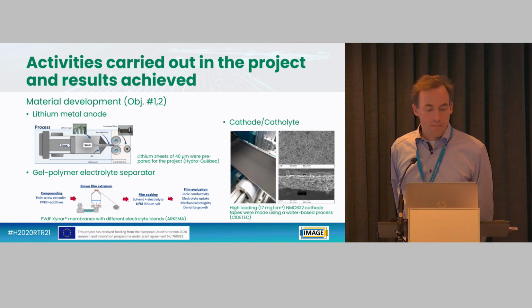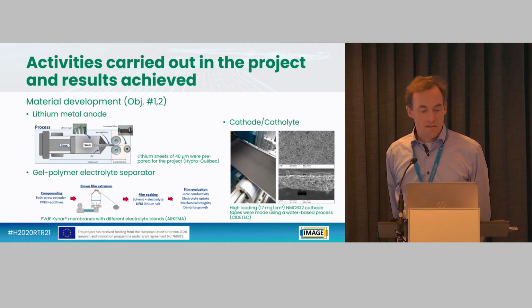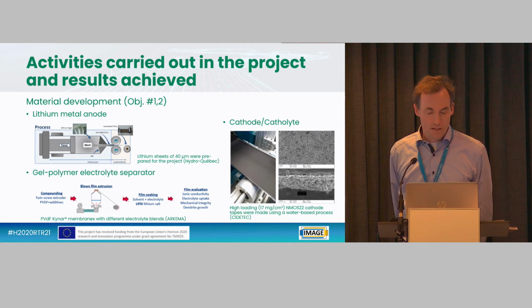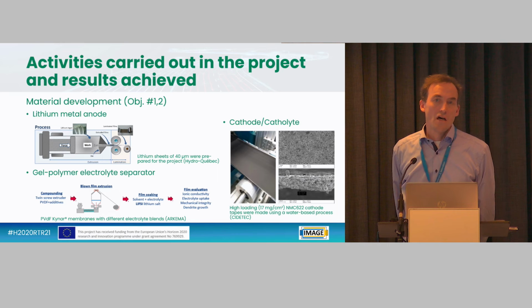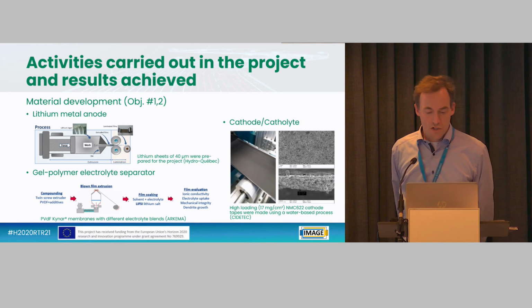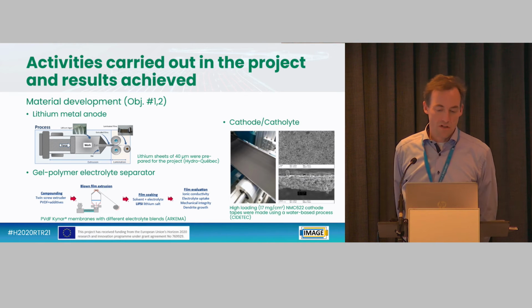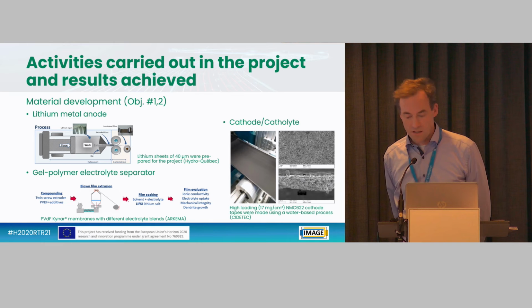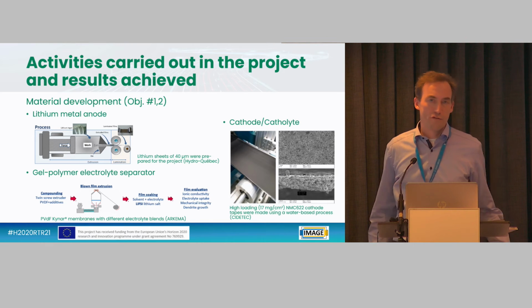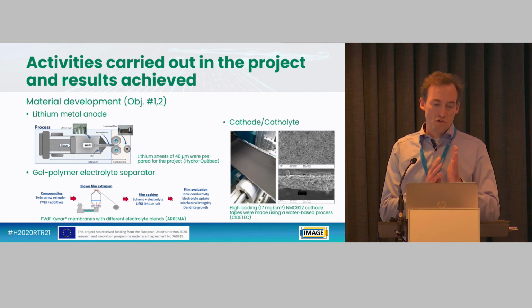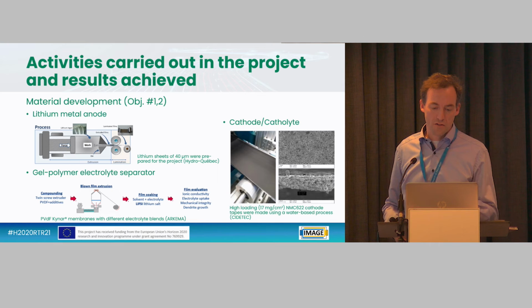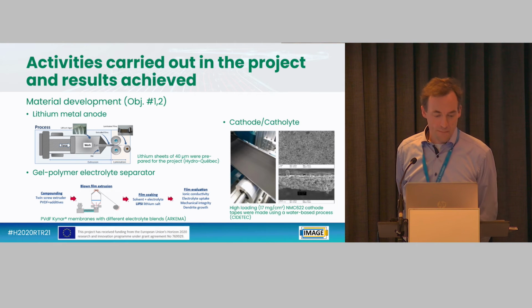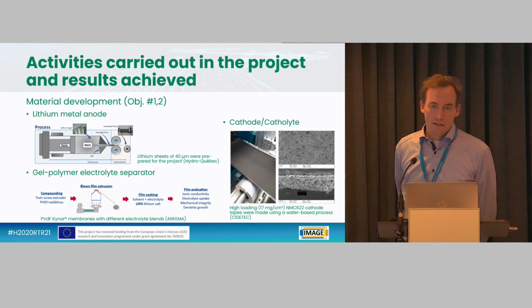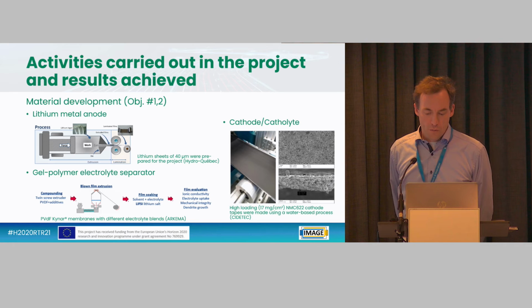So to go into the field of material development, the highlights: we used lithium metal foils of 40 micrometers. Thinner sheets are possible; 20 microns are possible, 30 microns are possible. If you want to go for an anode which is not supported mechanically by a current collector, you rather go for 40 microns. The cathode, the NMC, was from Umicore, as mentioned.